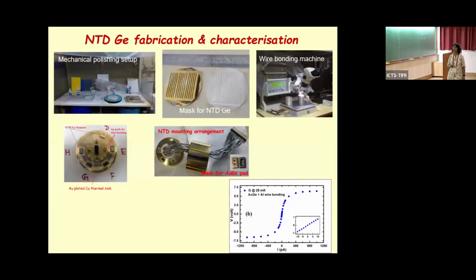Now you get into the sensor fabrication. The surface again needs to be shiny, clean, and smooth to avoid leakage paths. So you have to polish the crystals after they come out of a reactor. You have to etch them because the surfaces seem to have some additional radioactive impurities. So all that is done.